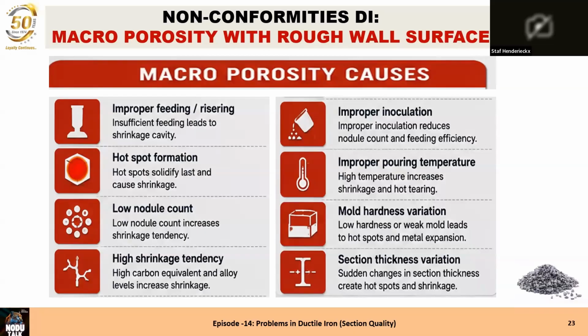Improper pouring temperature is another thing, because if the pouring temperature is high, we first have liquid metal shrinkage between the pouring temperature and the start of solidification. This shrinkage already has to be compensated by the riser, and then later it must also compensate the solidification shrinkage itself. It's better to have a low pouring temperature.